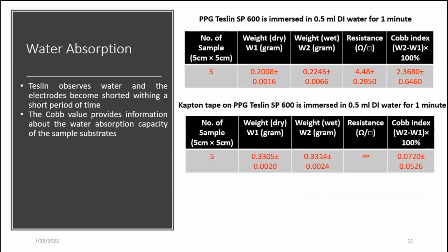We went through some further observation, and we saw that the substrate was porous, so it was actually absorbing the water while we were performing electrochemical analysis. So we took some quick samples of 5 centimeter by 5 centimeter. We put that in 0.5 milliliter DI water, and just after a minute, we saw that the conductivity is way higher. It is like 4.48 ohm per square resistance. So everything is shorted right after a minute.